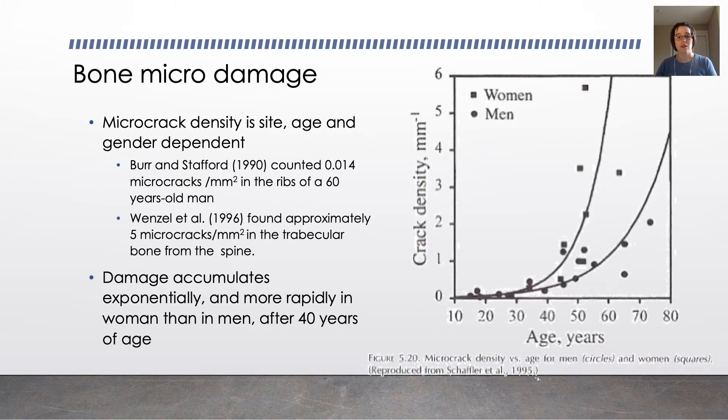Regardless, it's apparent that damage accumulates exponentially and more rapidly in women than men after the age of 40. You can see in this graph the women, the squares, and the men with the circles, both of them experience exponential growth starting at about age 40, women more rapidly than men.